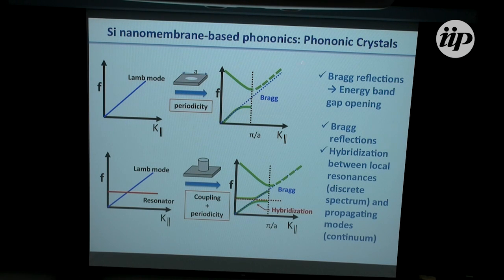So our dispersion relation would look something like this. And this is with respect to the plane, the parallel. But if on the other hand, instead of making a hole, we add a set of resonators periodically positioned, then we would have the interaction of Lamb waves with the resonator frequencies. In fact, there is then a coupling of these, and with the periodicity, we have effectively this dispersion relation plus the resonator mode leading to hybridization. And that means that we have, of course, Bragg reflection, hybridization, and then we would have both propagating and non-propagating modes.